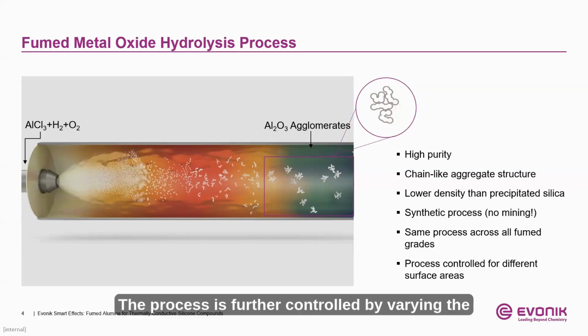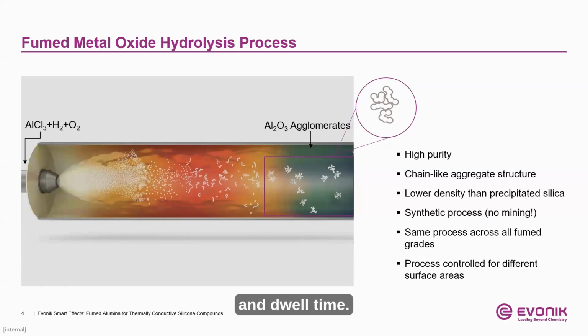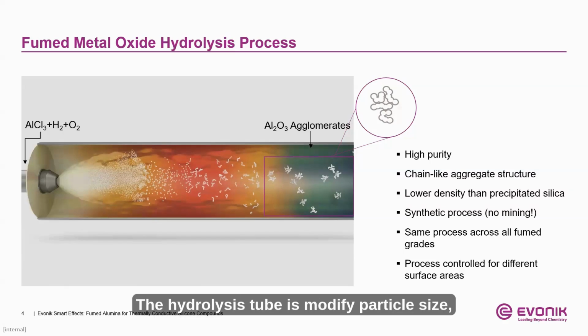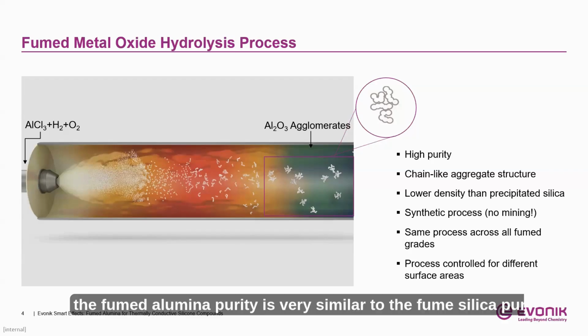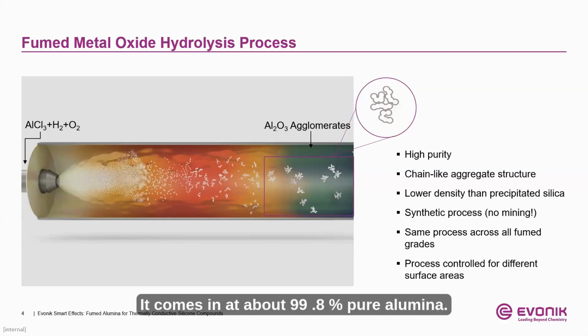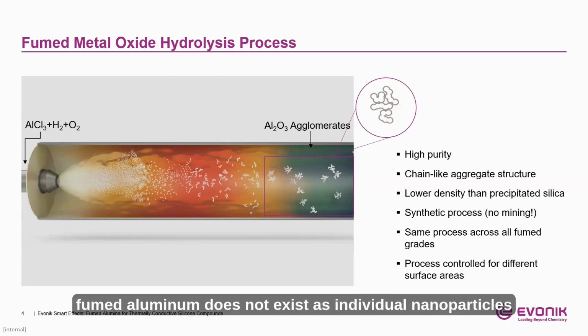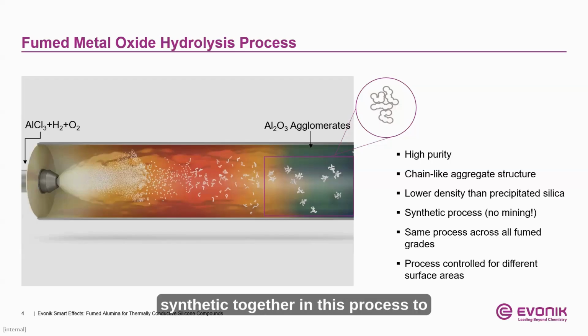The process is further controlled by varying the concentration of reactants, flame temperature, and dwell time in the hydrolysis tube to modify particle size, distribution, and surface area. Overall, the fumed alumina purity is very similar to the fumed silica purity. It comes in at about 99.8% pure alumina. Again, much like fumed silica, fumed alumina does not exist as individual nanoparticles, as I said, but rather groupings of nanoparticles that are permanently sintered together in this process to create the